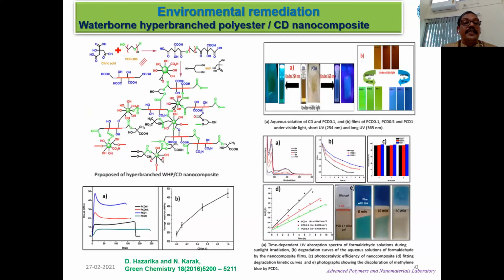Let's see: waterborne hyperbranched polyester and carbon dot nanocomposites are obtained. Here we use the carbon dot as one of the reactants, and most importantly, we have not used any external catalyst, solvent, or neutralizing agent. This is a really environmentally friendly approach through which we got this polymer nanocomposite, which exhibited good mechanical property along with photoluminescence characteristics. Most importantly, this surface is self-cleaning — under exposure of sunlight, it can degrade different dye molecules, giving you a self-cleaning surface.